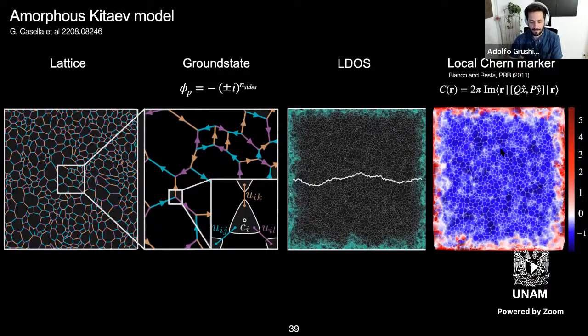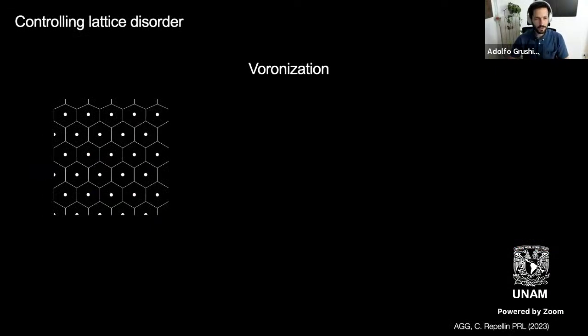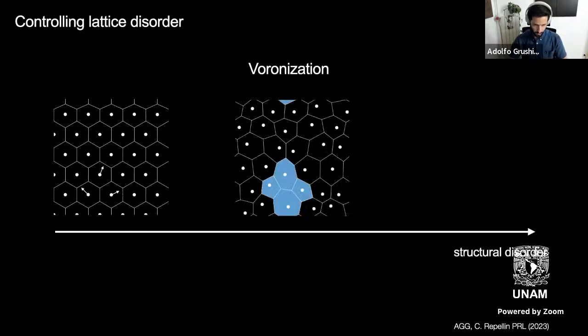Now what's interesting is: do we actually have to be fully amorphous to be in this topological phase, which is in fact the chiral spin liquid, because, as I was saying, it has chiral Majorana edge modes? The way we approached this question was to do again this Voronoi-ization, which for a triangular lattice, shown here in the white dots, means that you find the area closest to each dot, and you'll find a hexagon. Now, if you start displacing these hexagons by a little bit, a small value of disorder,